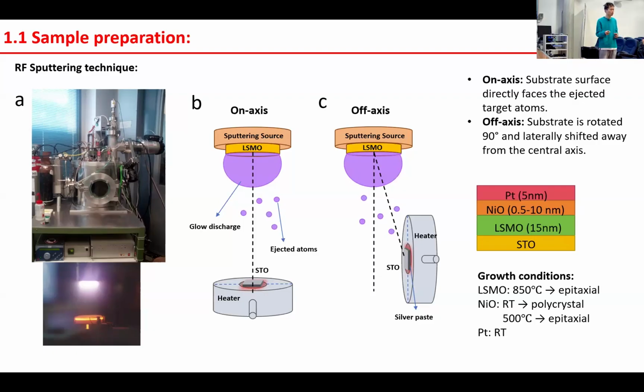Typically, the substrate is commercial, and easily processed, cleaned with acetone, methanol and so on, to achieve a very clean surface. We also measured the AFM image of the single STO. It shows a very flat surface. Maybe I did not put it in the manuscript, I don't remember. But it is a very flat surface. Very flat, but around the same roughness as the films? For example, the STO we measured below 0.2 nanometer, and once we grew the LSMO, we measured again, and it's also below 0.2 nanometer as well.